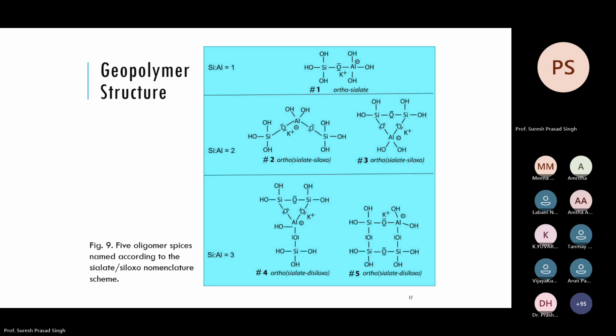So a structure like this is formed. And if the silicon to aluminum ratio is 2, this type of structure is formed, what you call sialate siloxo. Yeah. So here, the silicon to aluminum ratio is 2, this structure. And here, the silicon to aluminum ratio is 3. We have 3 silicons and 1 aluminum. This structure may be like this one or like this one. And here you see that this aluminum has a net negative, higher negative charge, which is balanced by a positive cation here, potassium, sodium. So this is the need for an alkaline cation, a positive cation, to balance the charge here.